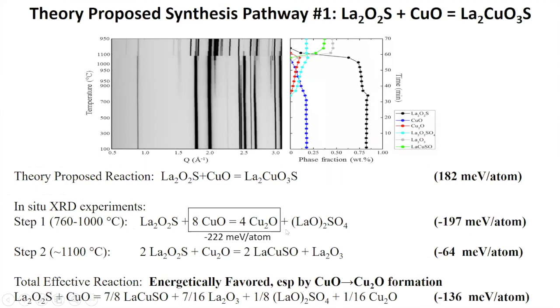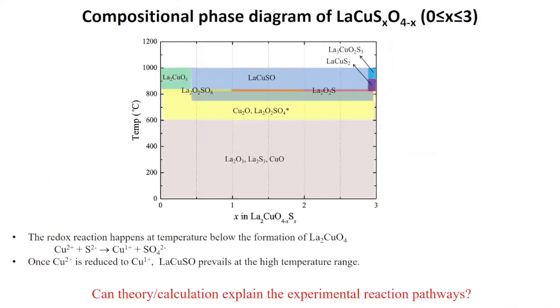And so I think that fundamentally the reason why it's impossible to put sulfur into copper oxide is this redox principle, which I think any chemist would have told you. So here is the conclusion of that experiment, which would just tell us that the basic problem is that redox reaction happens basically at all sulfur concentrations at a relatively low temperature, let's say at 600 degrees. And so that means that the copper is already reduced at low temperature. And since the lanthanum cuprate forms at high temperature, that's why this whole scheme falls apart.